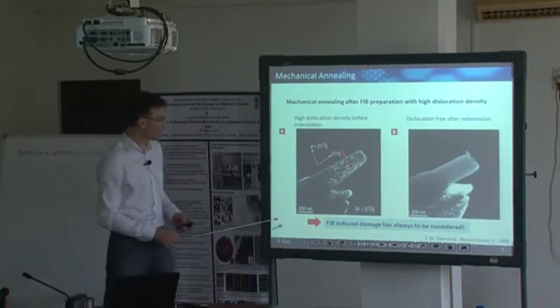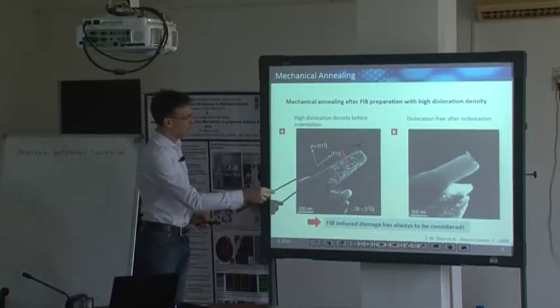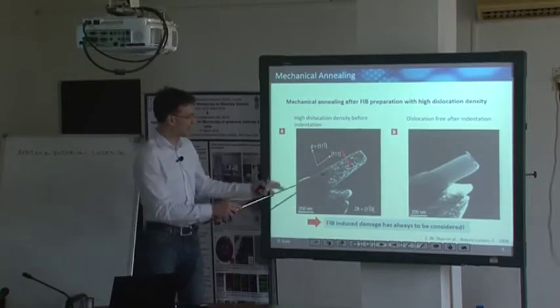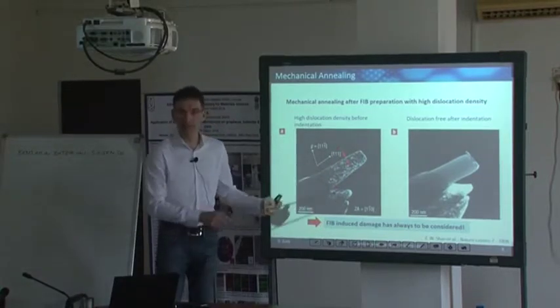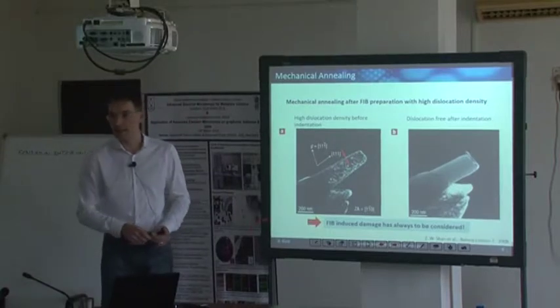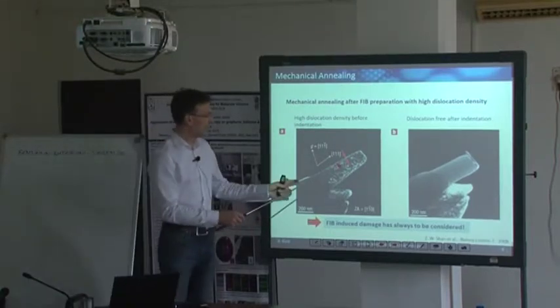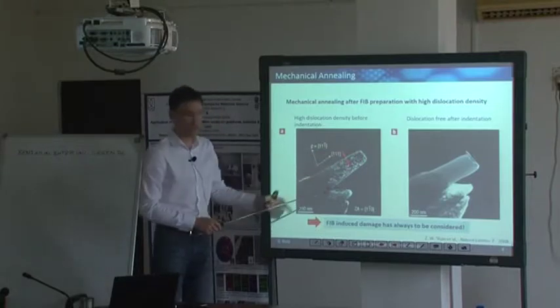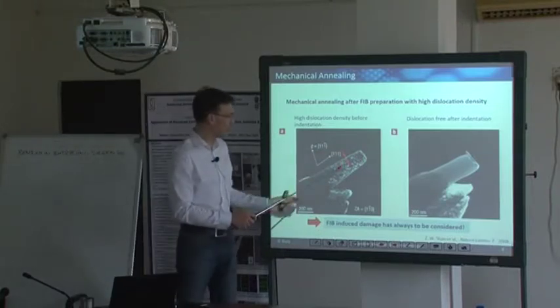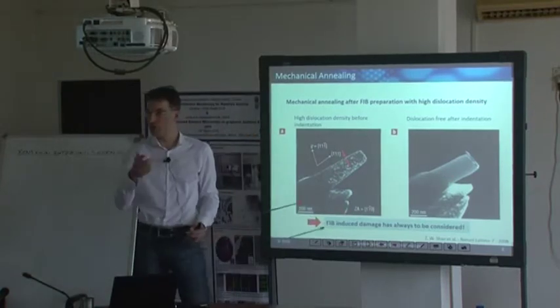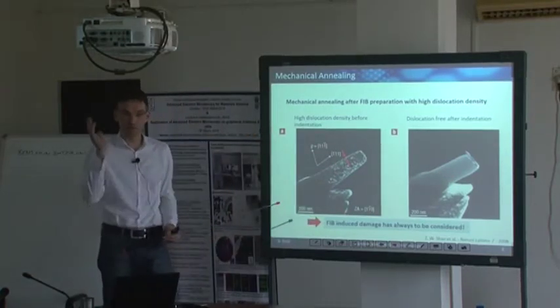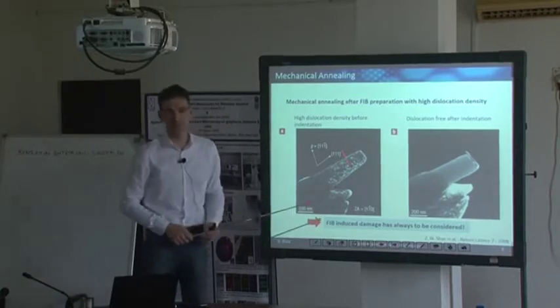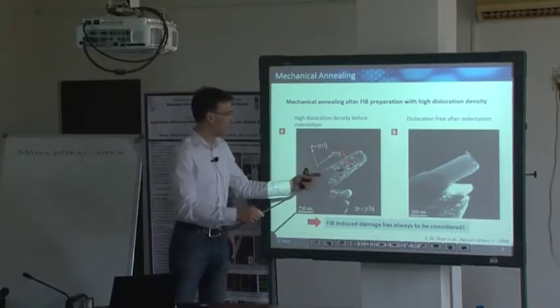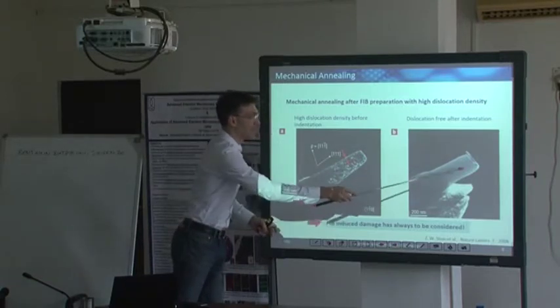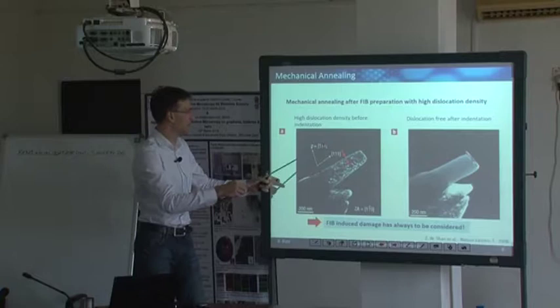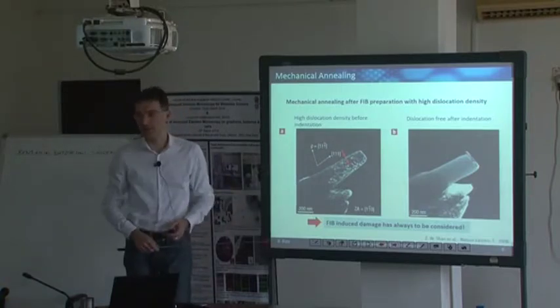This, for instance, is the cross-section of such a metal pillar in the transmission electron microscope, and here you see a very high density of dislocations simply due to the preparation using the ion mill, this ion milling procedure. And after mechanical testing, this is a very small structure, all those dislocations are gone because you have a huge surface area available, and they just moved out to the outer surfaces and disappeared. So this is probably the material how it would have been. This is just some artifacts generated by the focused ion beam.